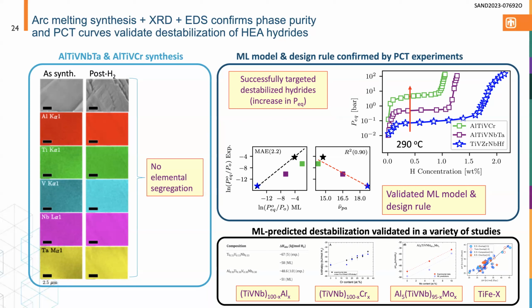And so we've been using this a lot recently with our experimental collaborators to target basically known high entropy alloys that seem promising, but their delta H's or their equilibrium plateau pressures are still too low. So it's turned out that this model is actually pretty good at predicting the shift in thermodynamic stability of these materials as a function of composition. And I won't get into all the details of all the different systems, but we've been using it pretty decently.